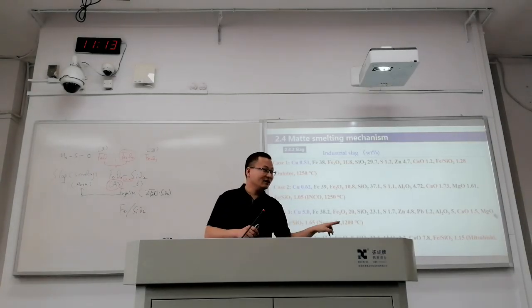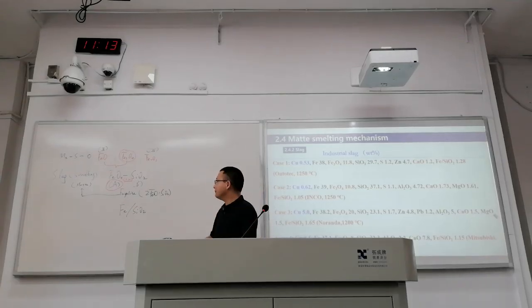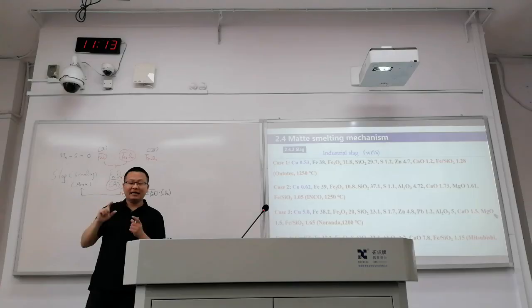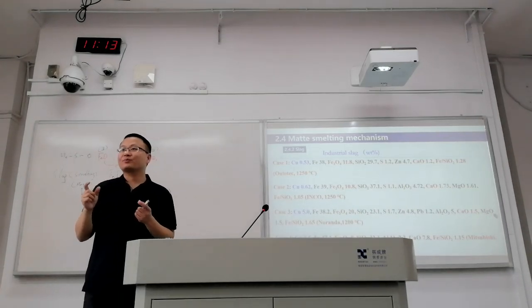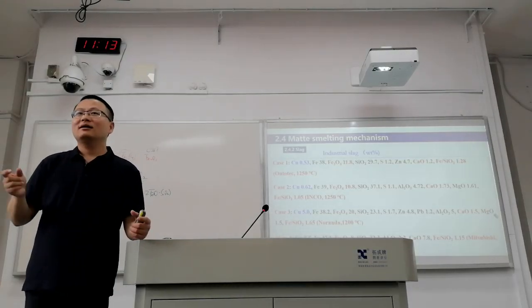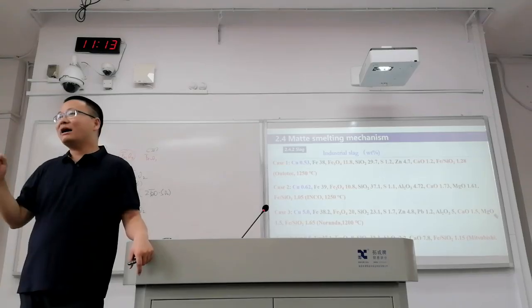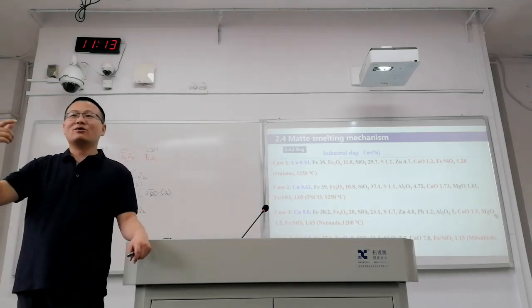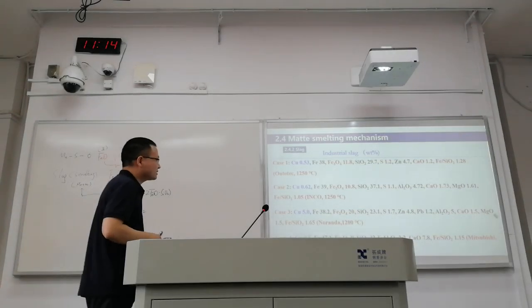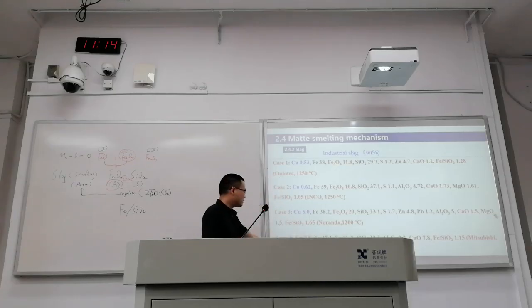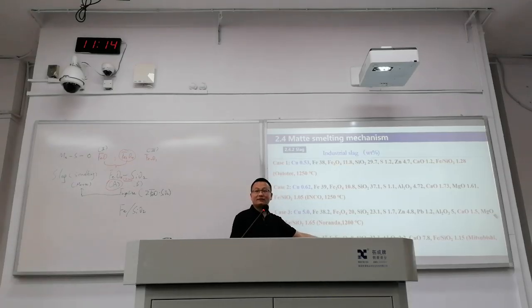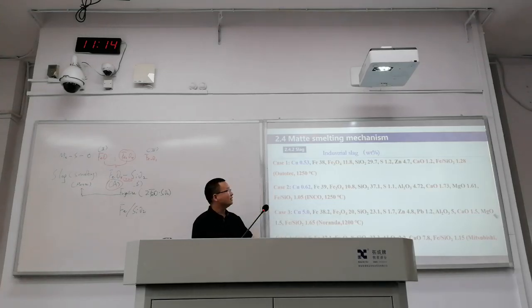So someone is giving an answer: over oxidized. Actually, the ratio between this one and this one can be an indicator of oxidation. If you are having pure ferrous oxide, it was reduced. When you are having pure magnetite, it is oxidized, and copper will be in the middle. The middle is the range. So this is magnetite, and for the last one is sulfide. It's lower, right? This is why this is a very good technology nowadays. This is actually from China. This is from Inco, used to be from Canada. The red one actually is used in South America. And this is from Japan, Canada, Indonesia.